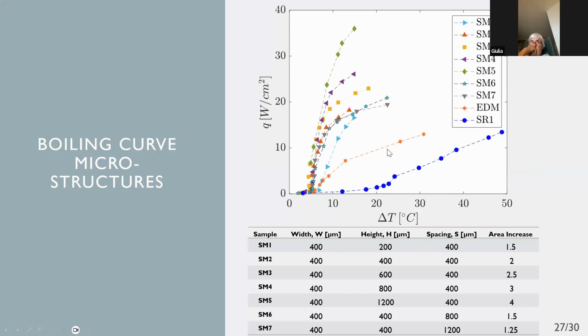And we can essentially see that, again, we have the smooth sample for comparison. This is the blue curve. And we can see that all the microstructure samples outperform the smooth one. In particular, the best performance is shown by SM5, which corresponds to the sample with the highest height. Again, these correspond to the highest increase of heat transfer surface area.